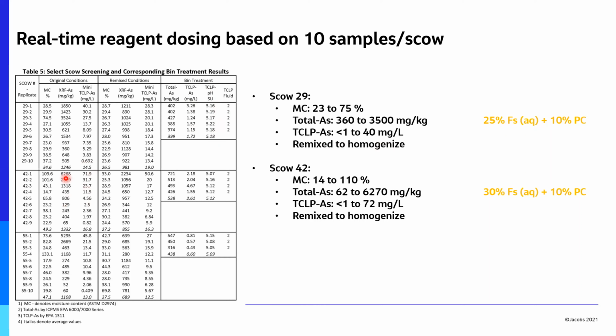Scow 42, we actually had on this one 6,300 milligrams per kilogram and a TCLP of 72. So we're way above our treatability study, right? We're almost double. We're like, that's not good. Let's go remix that one. We got it down to 50 as our hot spot. Okay, we evened that out. It was basically the same average, but now these doses are much more consistent except for that hot spot.